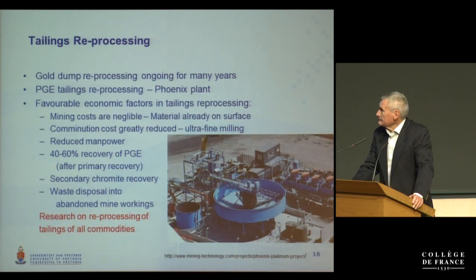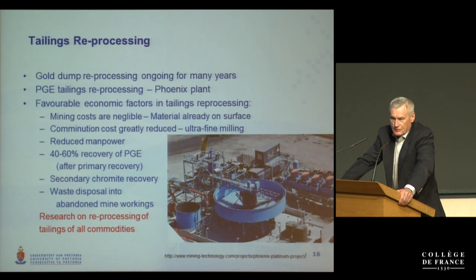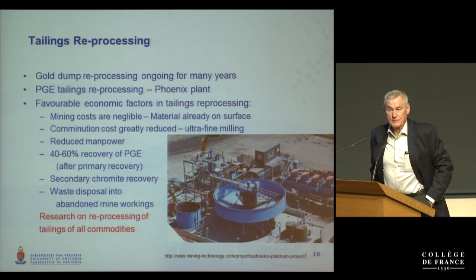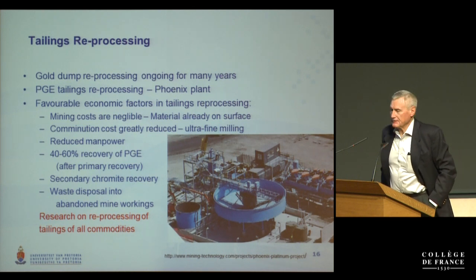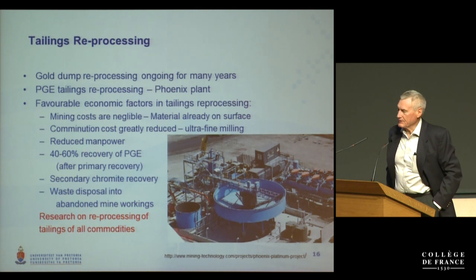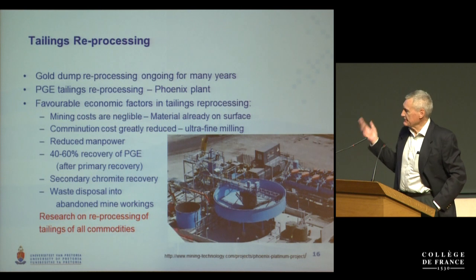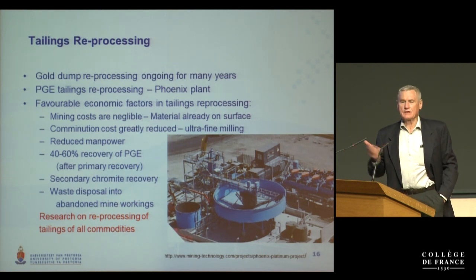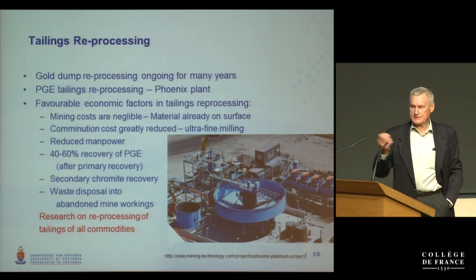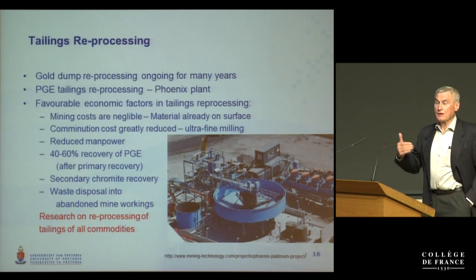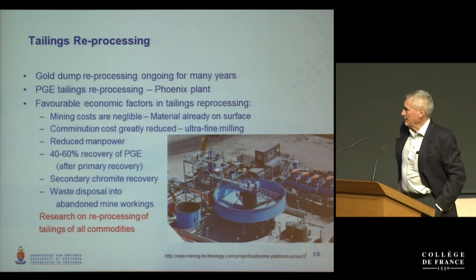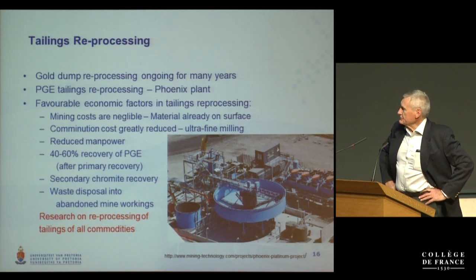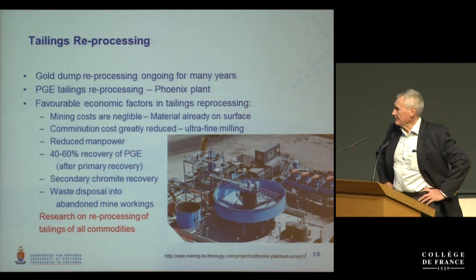The second one is tailings reprocessing. From the platinum group element industry, there's a lot of tailings present, tailings containing chromite, it's a so-called UG2 chromite, and also tailings containing still residual amounts of platinum group elements. Now, there is a strong economic incentive to look at tailings reprocessing. The mining cost is negligible because the stuff is already on the surface. The comminution or grinding cost is greatly reduced because the stuff is already minus 100 microns, sorry. And you can now start looking at ultrafine milling to liberate any locked platinum group minerals. Of course, reduced manpower, and you still get about 50% recovery after the primary recovery.